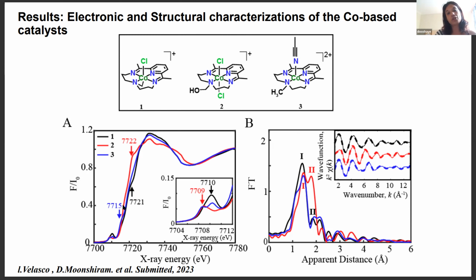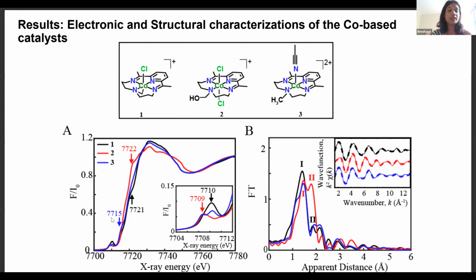They are typically observed in complexes with chloride ligands. So catalyst 2, with 2 chloride ligands, exhibits a much more intense 1s→4p plus shakedown transition in comparison to catalyst 1. On the other hand, catalyst 3, which is the cobalt-2 counterpart, shows a 1s→4pz transition at lower photon energy, which is assigned as the 4p on its pentacoordinated geometry.